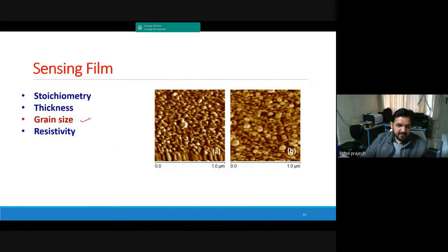The third point is grain size. You already know what grain size is. You can use AFM or XRD to find out the crystallite size or grain size. These grain sizes are important, as I told you, in the working of the device. You have these grains, and at the grain boundaries you get the adsorption of gases, and because of that there is a barrier height. This barrier height will either increase or decrease depending on the nature of the gas, whether it's an oxidizing gas or a reducing gas.